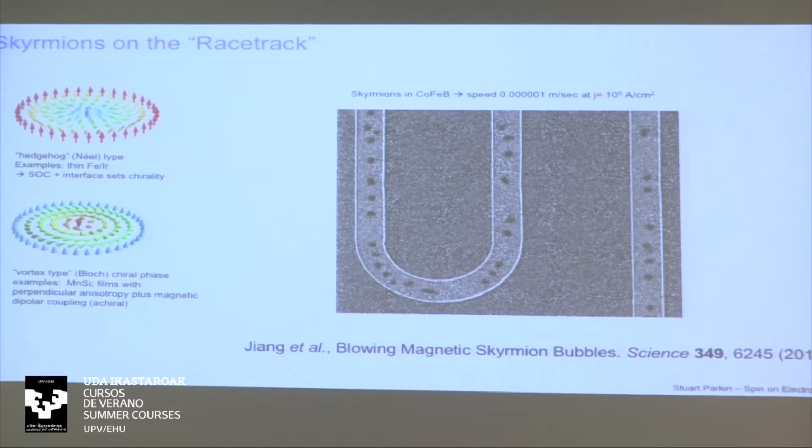Because of this Néel and Bloch type walls around the antiskyrmion, there are some crystalline directions in which the electron trajectory is not affected and other directions in which they'll be moved to the left and to the right. This is super interesting. With skyrmions, the trajectory is always twisted to the left or to the right, giving rise to this topological Hall effect.